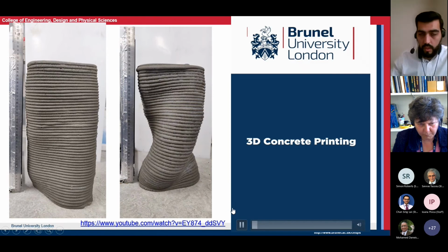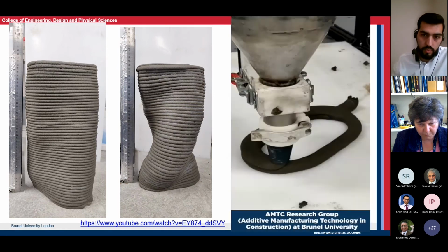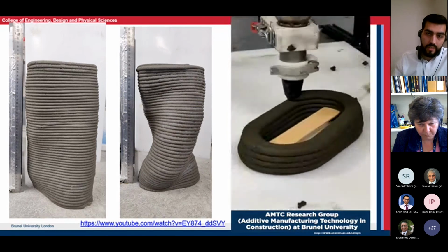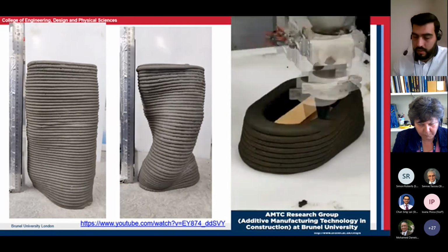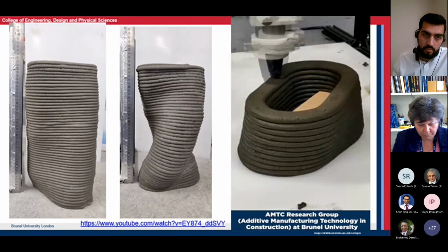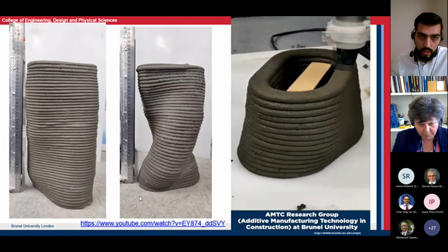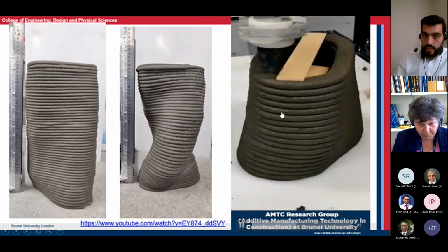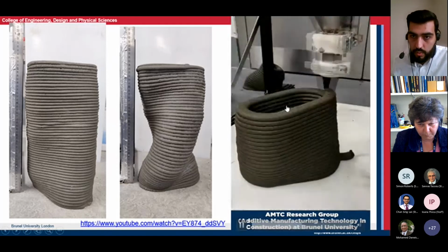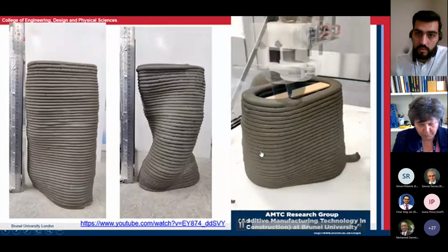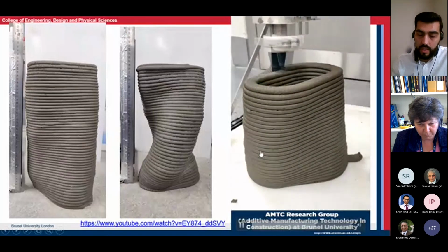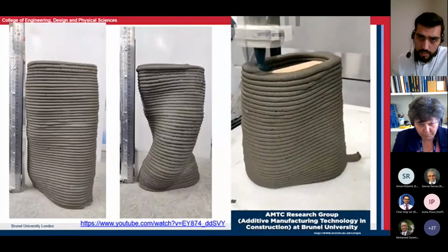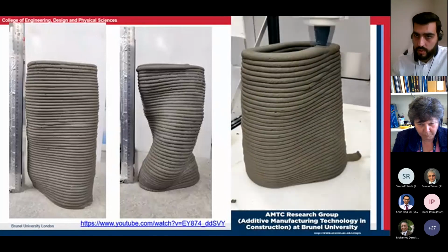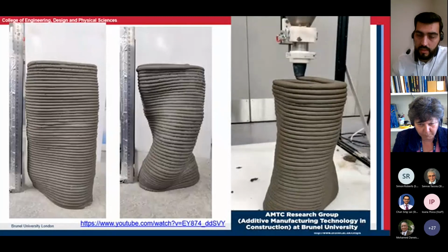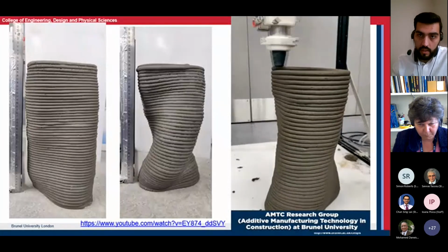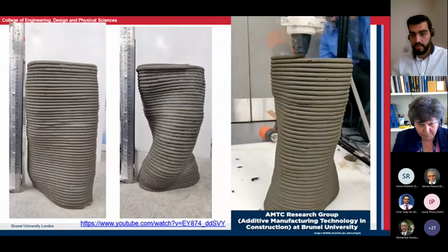Not only are they more sustainable compared to Portland cement, but they are more suitable for 3D printing application, and they actually result in much better results in terms of resolution and the print quality. And this is a video showing our geopolymer, which is using recycled sand and recycled waste brick. So the clay bricks that we have used here have been crushed into small sizes, and they replace the natural sand, which we are running out of, with these waste bricks.